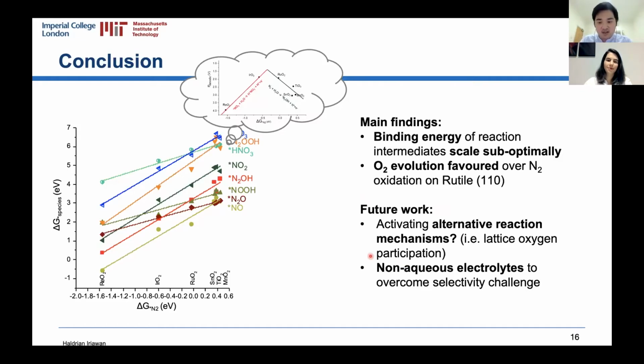And maybe for non-aqueous electrolytes, we can think about using some organic electrolytes to suppress the activity of water. However, this might be a bit challenging because it really depends on the stability window of these non-aqueous electrolytes. And we can see that nitrogen oxidation requires highly oxidizing potential. So the second alternative might be more challenging, but there are some select non-aqueous electrolytes that can be stable in oxidizing conditions.